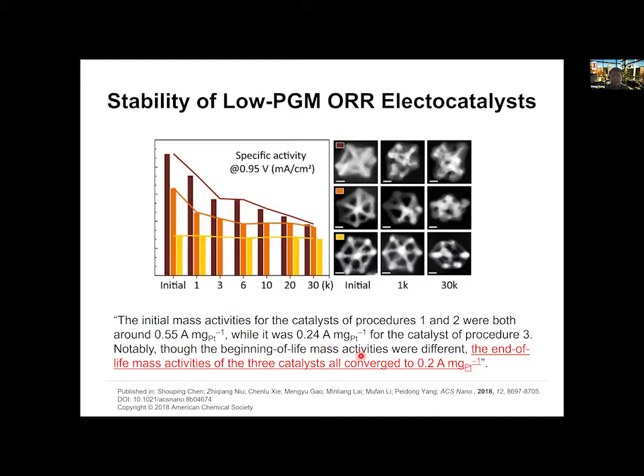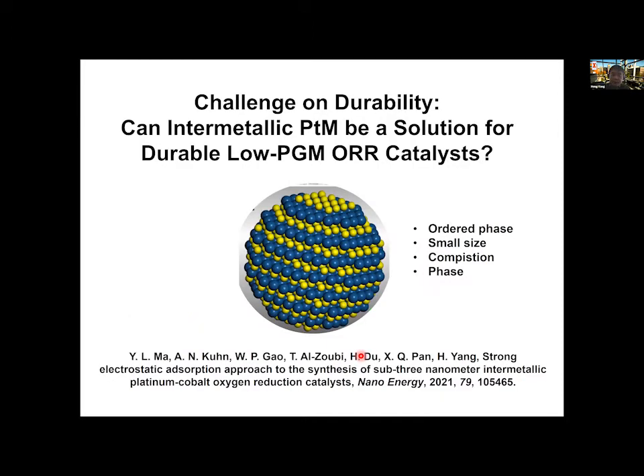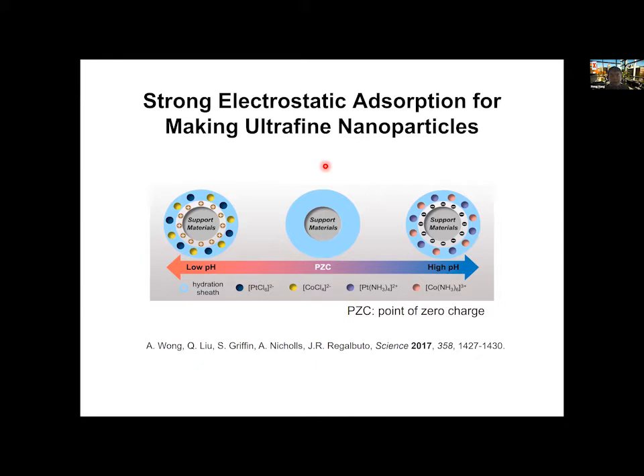So what we try to do these days, at least in one study that I'm going to share with you today, is to see what kind of stable intermetallic structure we can develop at very ultra-low features, and hopefully at a high density on the carbon support. This particular study is primarily based on the paper we recently published in Nano Energy. One of the systems we picked is platinum cobalt as the low PGM catalyst. The immediate thought behind the approach development is to see whether it can improve the density of the platinum cobalt catalyst on the carbon support. And so this leads